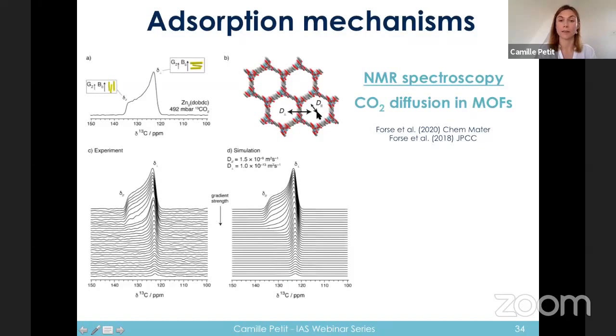Depending on the orientation of the MOF crystallite and the typical diffusion of CO2 within the pores and across the pores, there will be different signal for CO2. And so as the pressure of CO2 in the system is increased, you'll have a different pattern for that carbon-13 NMR peak, which can in a way be used to extract the information on the diffusivity of CO2 within those channels. And that was published in those two papers by Alexander Forse here.